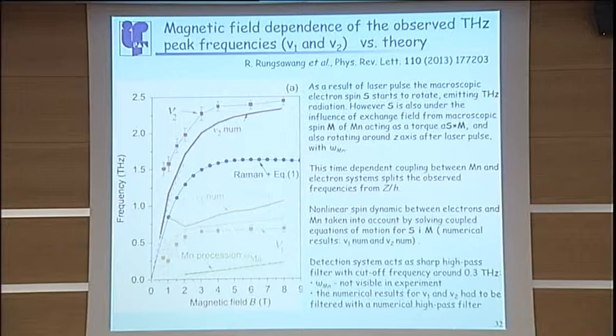But in order to bring this closer to the experiment, they also had to include the fact that the experimental setup was working as a high-pass filter with a cutoff frequency of 0.3 terahertz. So they performed numerical filtering of this numerical data, and they brought the filtered nu 1 closer to the experimental frequency. So the agreement is quite reasonable.